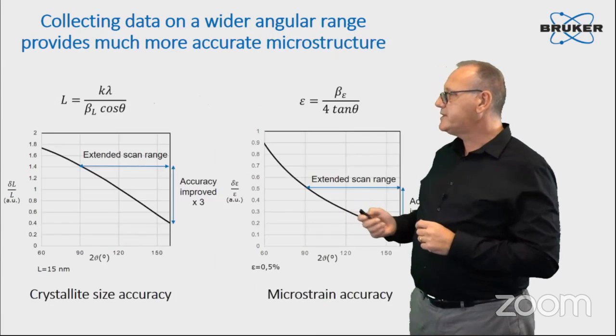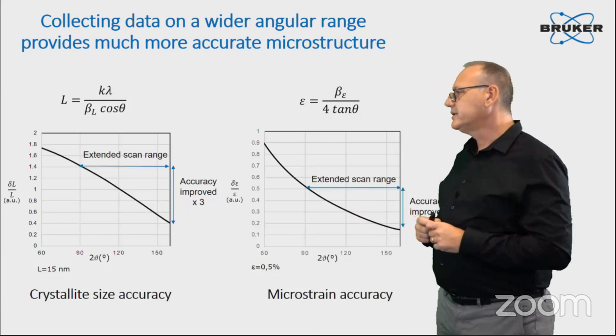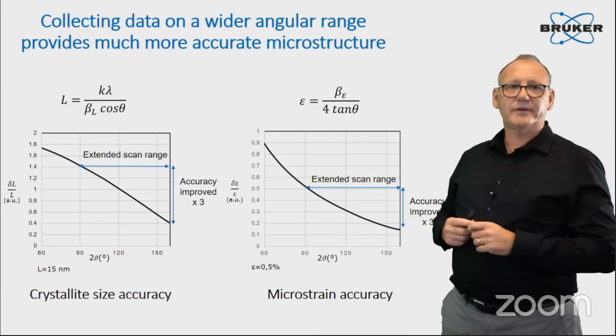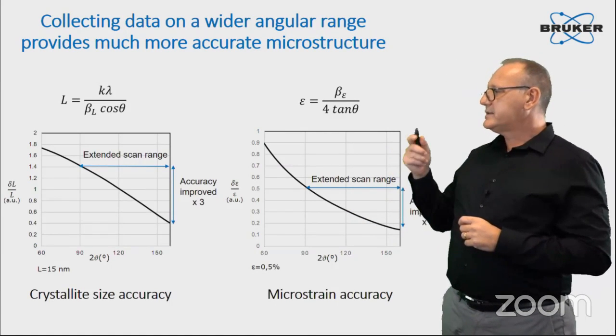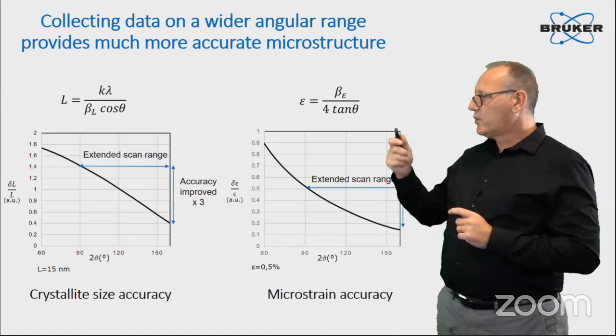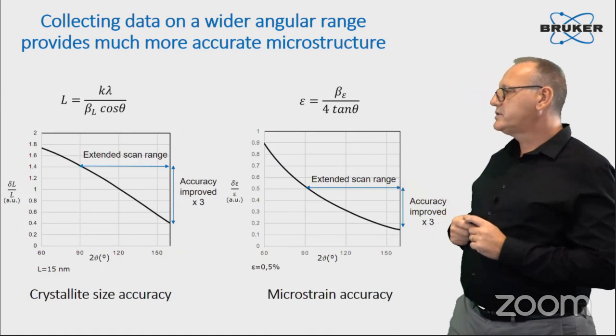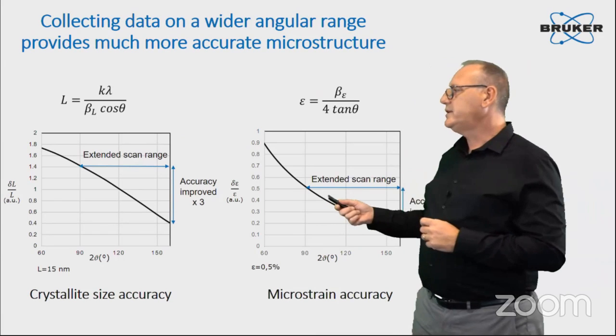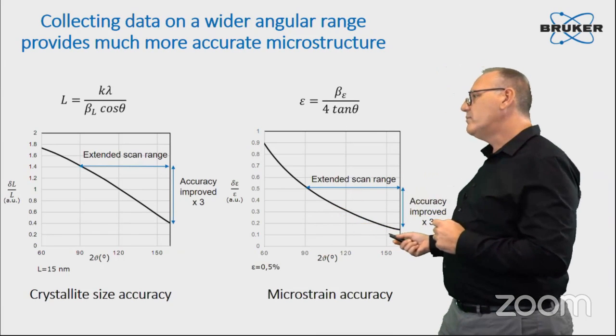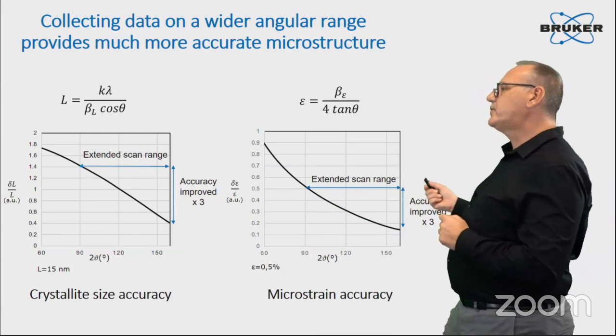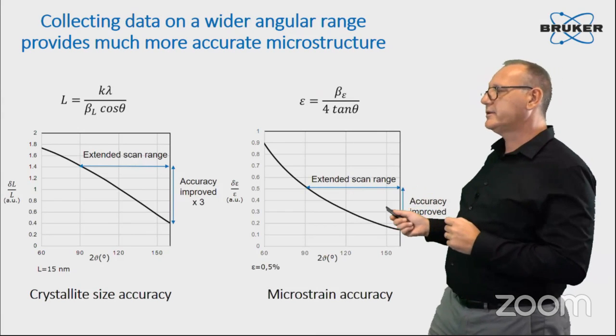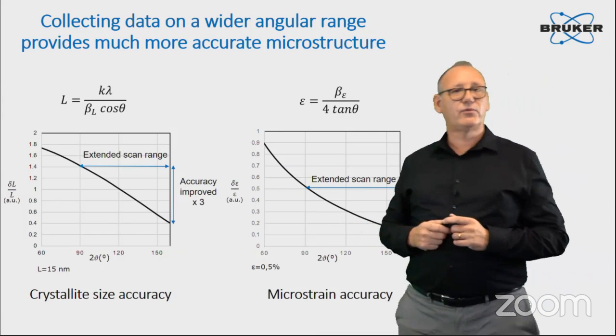This improvement is also observed for other parameters, the microstructure parameters, crystallite size and microstrain. They have those angular dependencies. And you see again, if you measure up to 90 degrees, or if you measure up to the maximum angular range, you will increase the accuracy on those parameters, for both parameters, by a factor of 3.